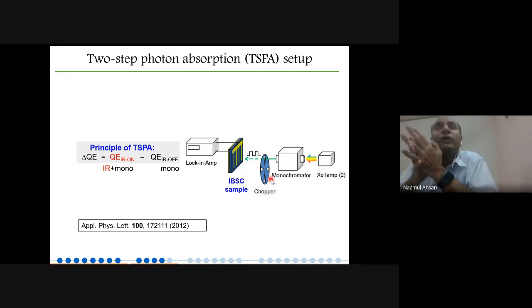So to do that, we have a 2 photon absorption setup, where you put in 2 long wavelength photons, and you make sure that out of the 2 photons you can generate 1 pair of electron and hole. We have this kind of setup, and this is the first paper where we demonstrated that, using this material, the first demonstration of room temperature 2 photon absorption in this material. And we have 2 photon here. Does it?